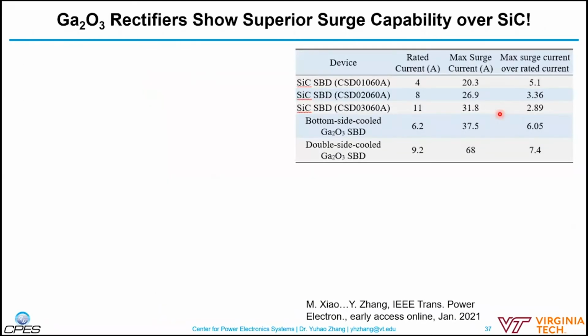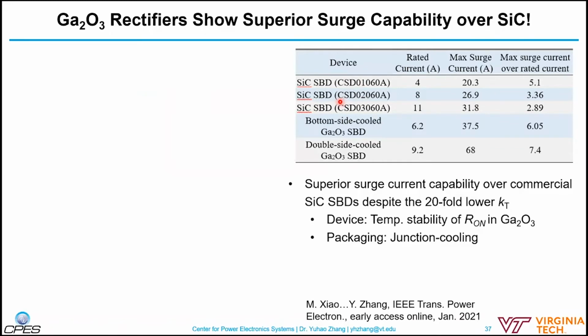Okay, and if we benchmark the surge current capability against commercial silicon carbide devices, we saw some very interesting findings. Here these are the commercial silicon carbide Schottky barrier diodes with different rated currents. This is the maximum surge current that we tested in the same circuit that we built, and this is our gallium oxide Schottky barrier diodes. If we look at the maximum surge current over the rated current, the gallium oxide devices actually offer a higher surge current capability compared to commercial silicon carbide devices, despite the much lower thermal conductivity of gallium oxide.